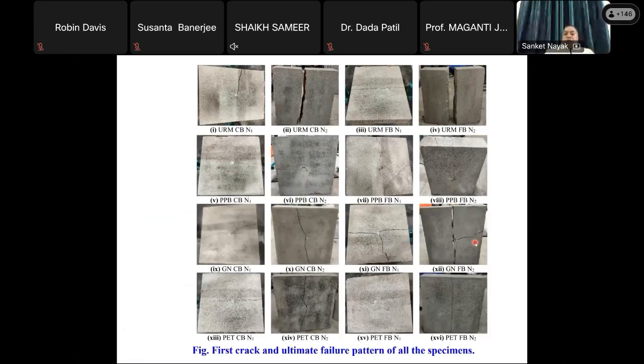This is the failure trend from the first crack to the final failure. If it is the unreinforced one, you can see this is N1, then it is N2. For the clay brick and the fly ash brick, it is N1 and N2. N1 means after the hit, the first crack appears, and N2 is the case where complete failure has occurred, and we do not have to give any other blow, and it is complete separation, there is no strengthening. But in a similar case with the PP band, after repeated blows, though it is damaged, it is not complete separation, the integrity of the wall is maintained. Similarly for other cases also.